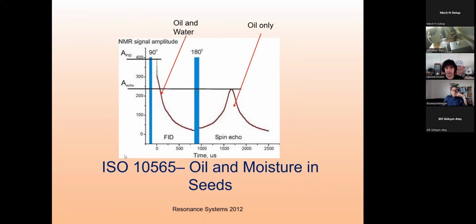Then measurement of the oil in seeds. This is the next standard. This is also an ISO standard, and there are analogs from ASTM. You look at components with different relaxation. If you take seeds from, let's say, sunflower, they always contain some small amount of water, and they contain some amount of oil. The more oil they contain, the better, because you can get more oil from the harvest. Understanding that the oil has a longer relaxation time and water has a shorter one, you can use a simple spin-echo experiment: the amplitude of the echo is proportional only to oil, and the signal of the FID is proportional to oil and water. Using some calibration, you can immediately measure the content of oil in seeds. It takes about 1 minute or even less. So it means that the method is quite informative.